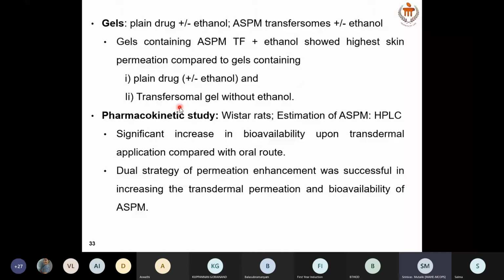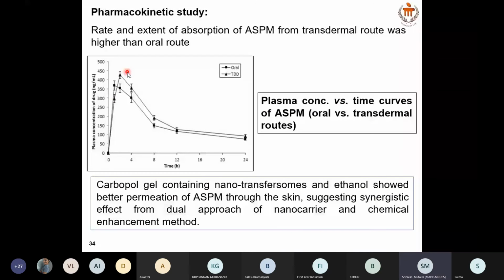Then we also conducted a pharmacokinetics study. Here we applied the gel containing transfersomes and ethanol onto the rats, and then took the blood samples at different time intervals and analyzed for the drug release. And there was an increase in the permeation of the drug from the gel into the blood at different time intervals